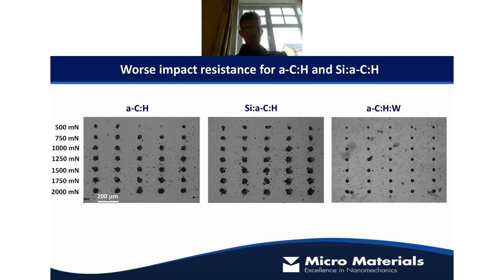And when we compare these three different systems, if you remember, this is the hardest one with the best wear resistance in most sliding tests. This one has actually lower wear resistance in the sliding test, but nevertheless, you can see in terms of impact resistance, much more cracking resistance. So you're getting a sort of indentation type crater, not a cracking failure. You see a couple of ones here where it hasn't failed.